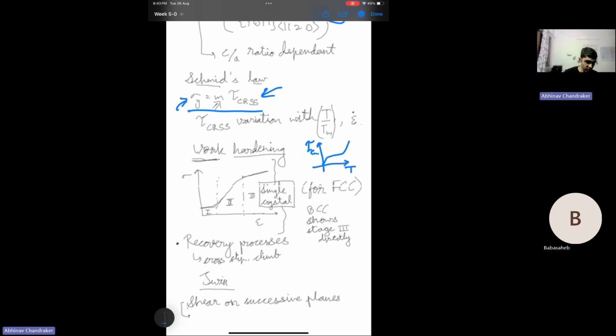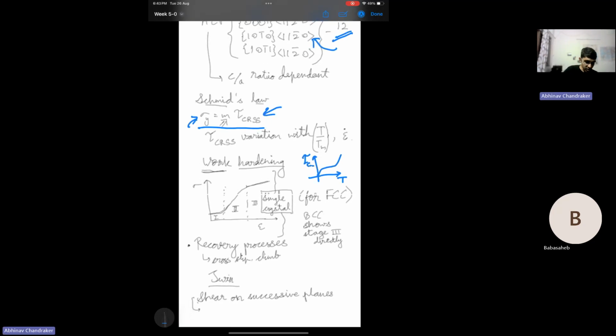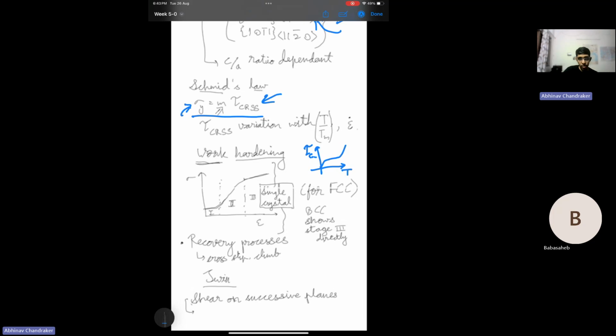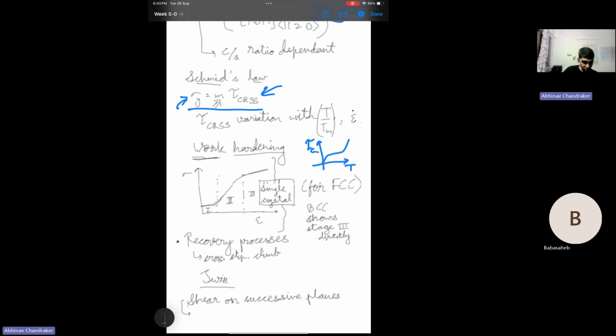It will also vary with the strain rate because deformation strength is strain rate dependent, and it's important to keep that in mind when you are designing things. Strain rate will have an effect on how much strength your material can bear. Shock loading and creep loading will have very different effects on the material.